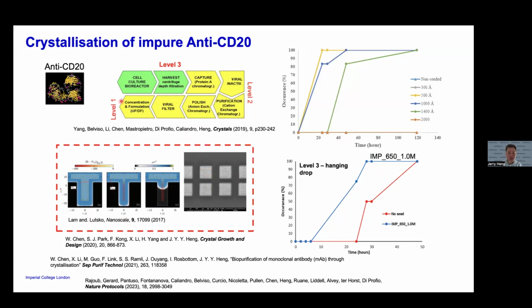The key result here is that we're able then to crystallize anti-CD20 out of level 3. Out of level 3 means that the solution that we started off with was really just post-DEF filtration, without any protein A or anion exchange or cation exchange filtration. So those were not pre-purified or pre-concentrated solutions. I would imagine that for downstream costs, there would be a significant reduction in cost if one could crystallize out from level 3, as we exemplify here in the case of anti-CD20.